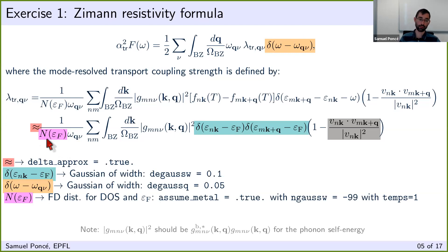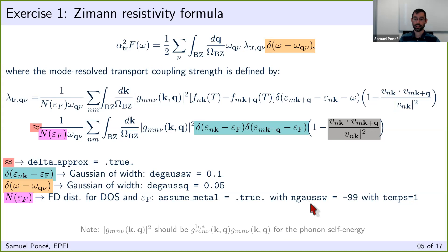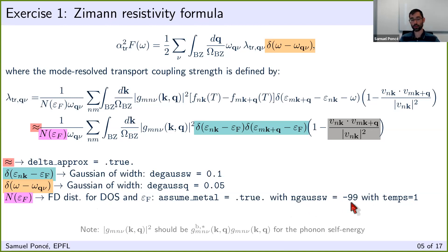In the denominator we have the density of states at the Fermi level. For a metal, you set the input variable assume_metal, and the code computes this DOS using a Fermi-Dirac distribution function. In that case you need to use ngaussw = -99 from Quantum ESPRESSO, which means you want a Fermi distribution.